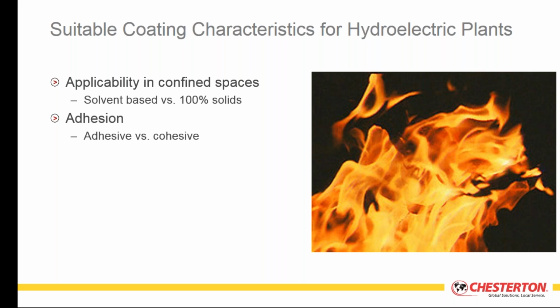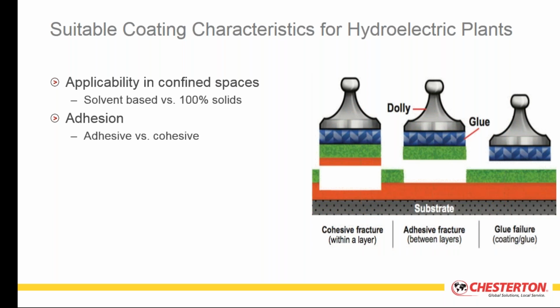You want to see, whenever possible, cohesive failure as opposed to adhesive failure. The beautiful thing about epoxies is that they were developed initially as an adhesive compound, back in the early 30s. These adhesive compounds develop extremely high tensile strengths, so that when they fail—and all coatings will fail, all materials will fail at a certain stress point—with these types of coating systems, they fail cohesively.